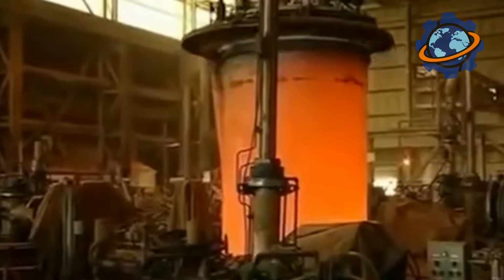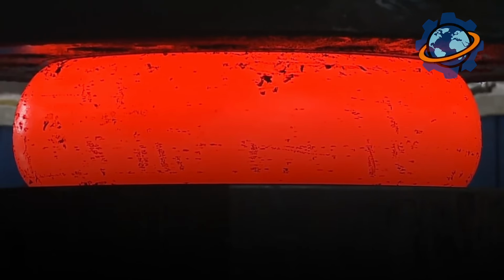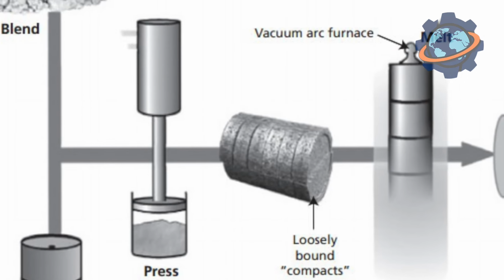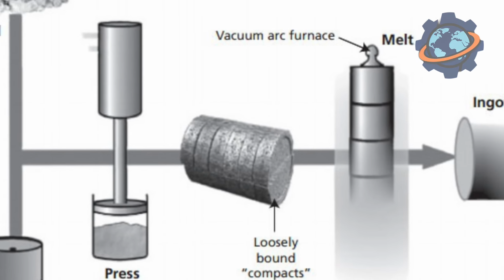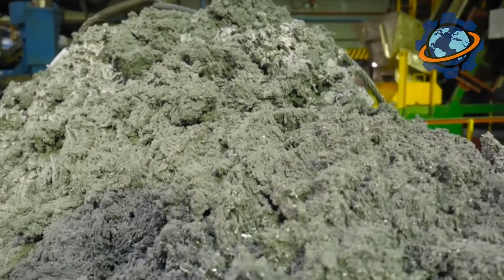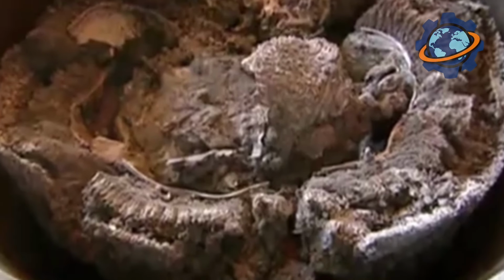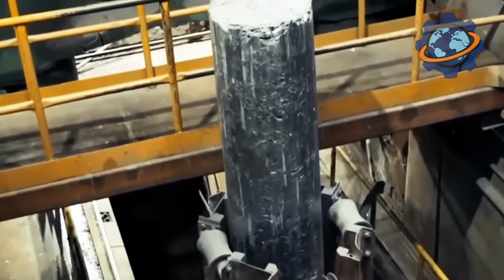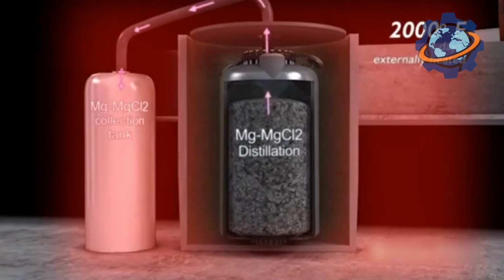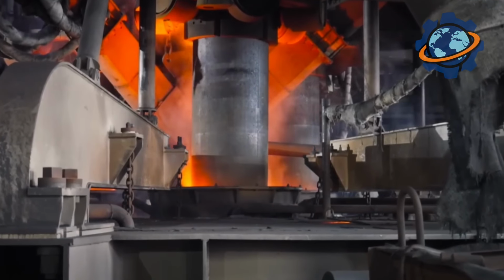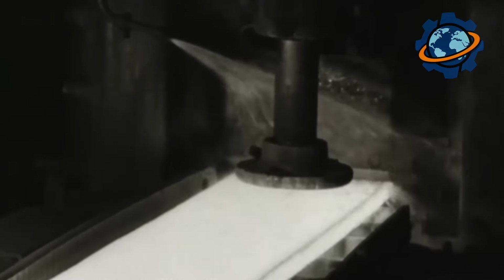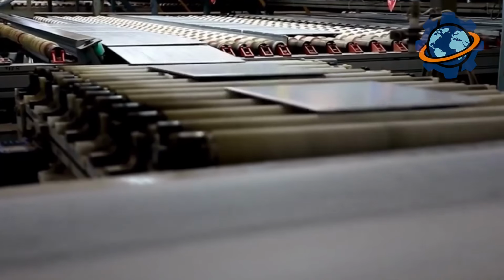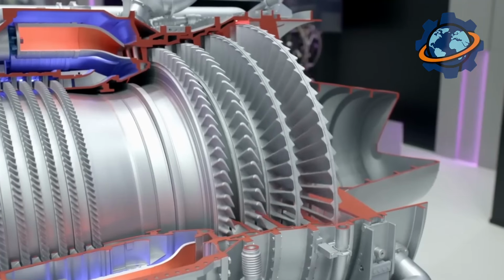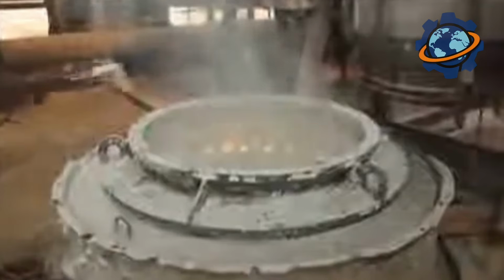The next key stage is the reduction of titanium tetrachloride to metallic titanium. The most common industrial method is the Kroll process, in which titanium tetrachloride reacts with magnesium in a vacuum chamber at high temperature. The result is titanium sponge, a porous metallic powder containing impurities of magnesium and magnesium chlorides. This reaction mass is subjected to vacuum distillation to remove impurities, after which the titanium sponge is pressed and remelted into solid ingots or slabs. The resulting titanium ingots are then used to produce alloys, rolled products, sheets, and complex parts. The entire process requires strict control of purity, temperature regimes, and safety, as titanium actively reacts with oxygen and nitrogen when heated.